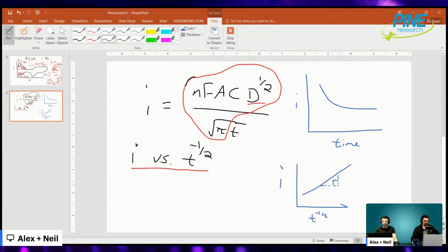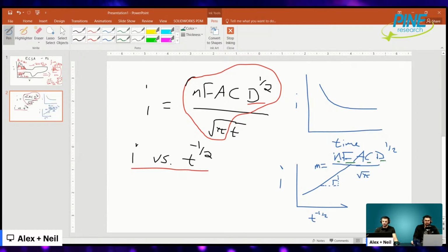Your slope is basically equivalent to NF A C D to the 1/2, and I guess there's a square root of pi in the denominator. The point is, if you know all of these constants here, if you know N, you know F is Faraday's constant, you know the concentration, and you can make an assumption of the diffusion coefficient, like something about your electrolyte, for example, then you can calculate A. This is a way to do it.